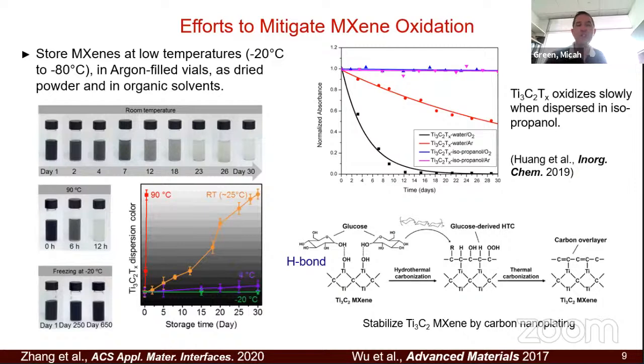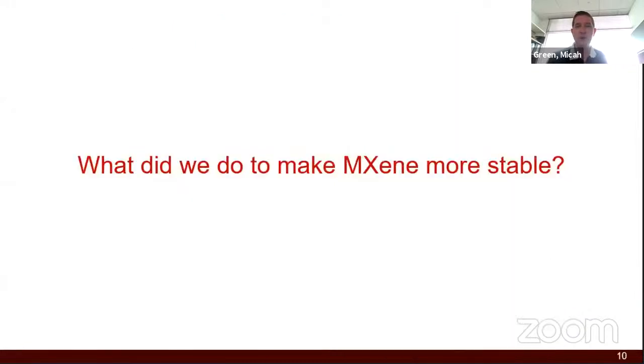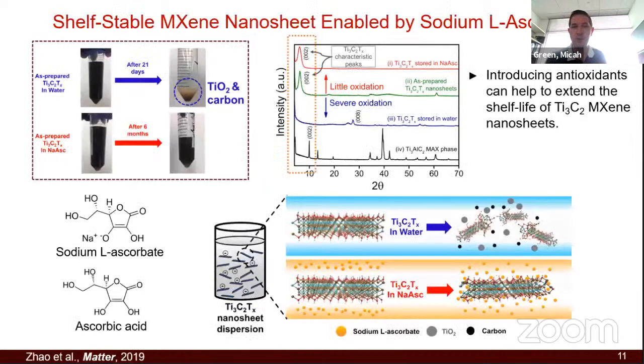So there's been a lot of work to try to mitigate oxidation. Some people have tried to use argon instead of humid air, or use other solvents other than water, like isopropanol. My group has done quite a bit in this area. You can freeze them, you can use them at low temperatures. But what we really worked on a lot is using antioxidants. I know that sounds obvious, but no one had really done it. No one had used antioxidants with MXene dispersions.